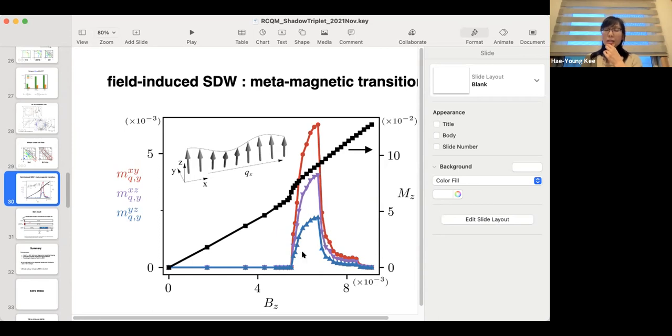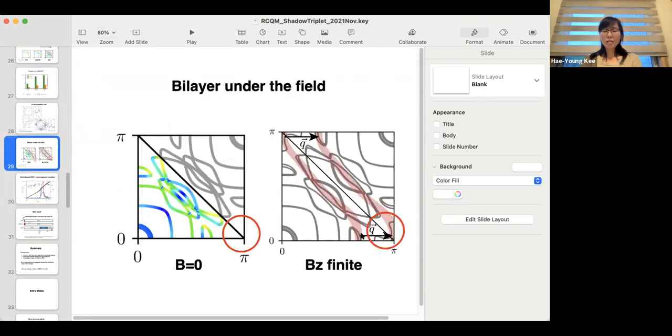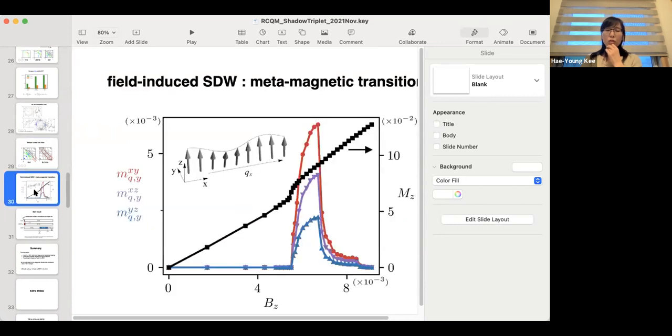This part here, spin density wave, is not the case. We found that if we change the tight binding parameters slightly, we do have a little bump here, which I don't know if that is a different phase at this point. And this window of the SDW can also change. I think that's because these are sensitive to the area near the gamma X point. So I don't have an answer for this B phase at this point.